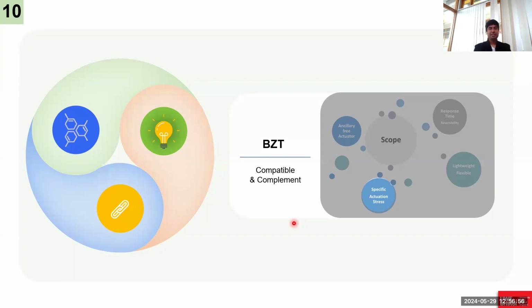And with the removal of these micro voids, the transparency of the polyethylene has been increased, which is also a benefit that we need, because if we are going to illuminate something with the light, it should be able to pass through it, and if the material is transparent within the visible region, that would be ideal for this case. And using BZT polyethylene with the high Young's modulus and the light as a remotely addressable material, we were aiming to create a specific actuation stress, because an oriented polyethylene material can generate a very high specific actuation stress because of its being lightweight.